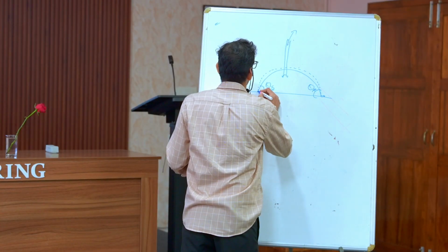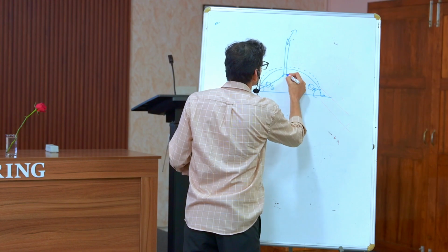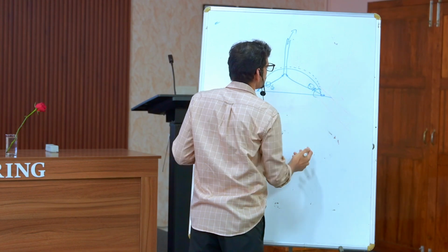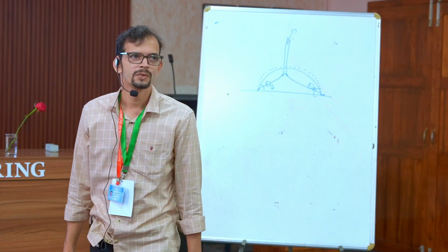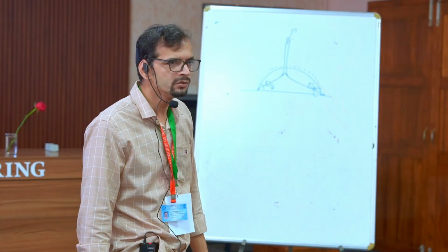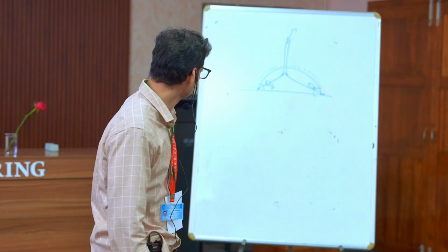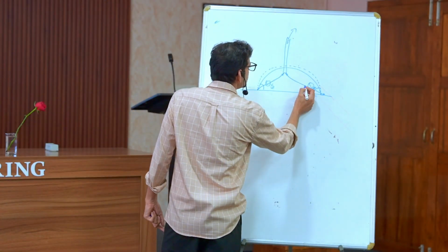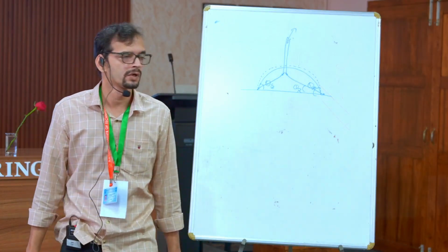And at a lower contact angle, only then will it start to recede. I drew it in an extreme case to convince you. It is not like this in all cases, but I am saying. And this angle is called the receding contact angle. That means you have an advancing contact angle and a receding contact angle.